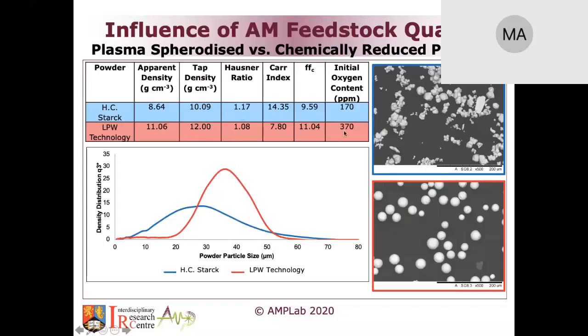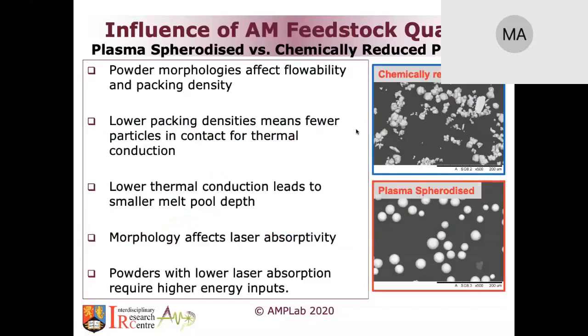Interestingly, the oxygen content of the faceted powder, the irregular shaped powder, was lower than the oxygen content of the spherical powder. And if you remember the numbers I was giving before, 170 and 370 means that regardless of which one you use, you're going to get cracks. This is way too high a level of oxygen for the material to take, and you're likely to get grain boundary cracks. But more importantly, we should look into why it matters.